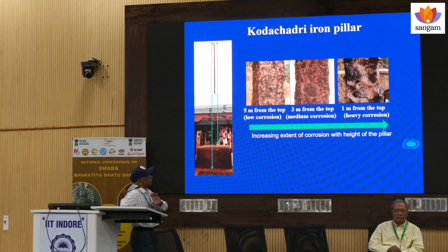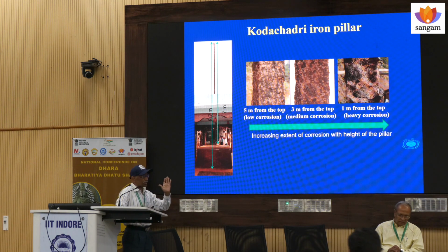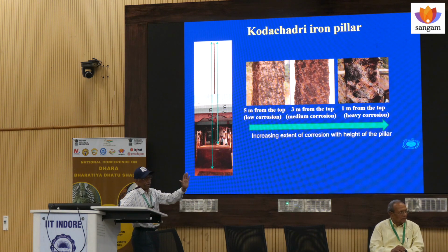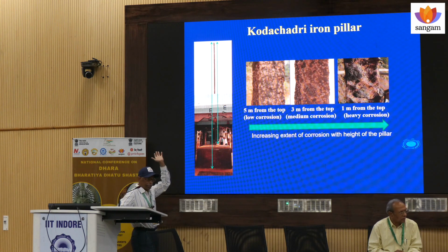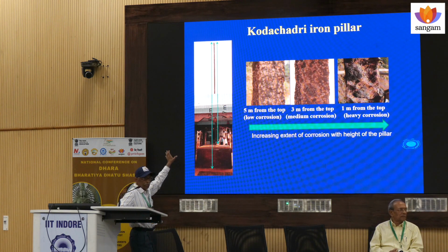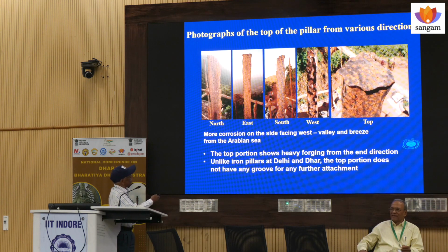So there is a tremendous difference with respect to the corrosion from the facing and also from the height, because at greater height, the sea breeze is coming directly, and it is having more corrosion effect. So we have done a lot of work. So you can see that in the west region the corrosion is more, and as you come to the opposite direction, particularly the east, there is a very small extent of corrosion.